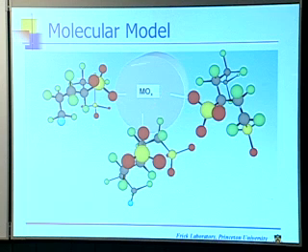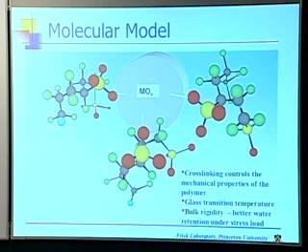But our picture would be something more like this, where there's a few sulfonic acids. There's your metal oxide particle. There's your 3 chains of the polymer. A few sulfonic acids that are interacting via this coordination interaction, tying this whole structure together like that. So this might be a fancy way, if you will, of doing some cross-linking if you were a polymer chemist, but not a strong type of cross-linking. These are very weak interactions. We can't see them easily spectroscopically. The only way we're seeing them is this indirect technique that I've described to you.